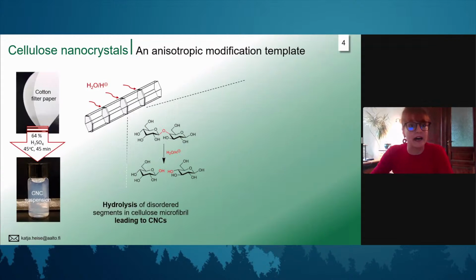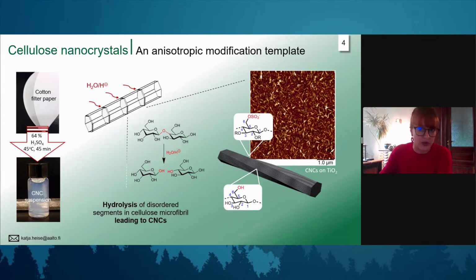Probably the most common pathway to isolate cellulose nanocrystals is sulfuric acid hydrolysis. If you start, for example, from cotton filter paper, you use 64 weight % sulfuric acid, and you obtain these nice bluish dispersions, which are already a sign for the excellent colloidal properties of cellulose nanocrystals. What happens during hydrolysis is that the acid attacks the disordered, so the amorphous, regions of our fibrils, and this leads to hydrolysis and to the cellulose nanocrystals. And these are rod-shaped particles.